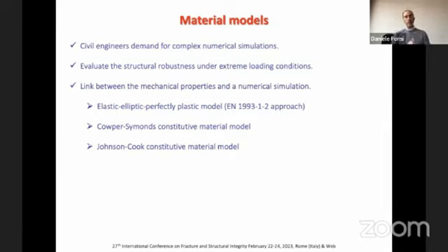So we have considered three different approaches. The first one is calibrating the experimental test results with the elastic perfectly plastic model proposed by the Eurocode 3, but under dynamic conditions. And the last two are the commonly used constitutive relationships describing the mechanical properties of metallic materials at high strain rates. The names are the Cowper-Symonds and the Johnson-Cook relationships.